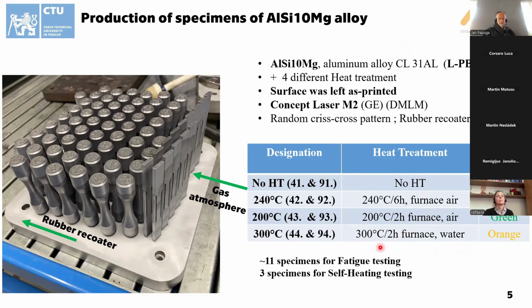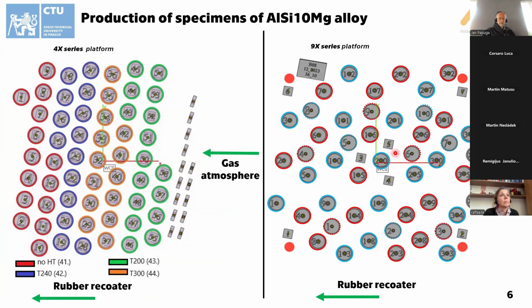For the SN curve, 11 specimens were used for fatigue testing to construct the SN curve, and 3 specimens were delegated for the self-heating tests. Also, at least 3 to 5 specimens were used for the tensile testing.